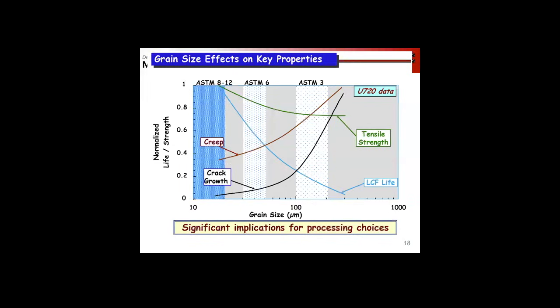And every time that spins up and shuts off, we've got fatigue. So for our discs, we want generally a smaller grain size. There's a big trend to try and do dual discs where you have coarser grains at the edge where you have temperature, and finer grains in the hub where you have fatigue cracking.